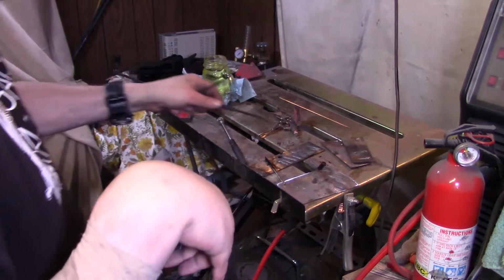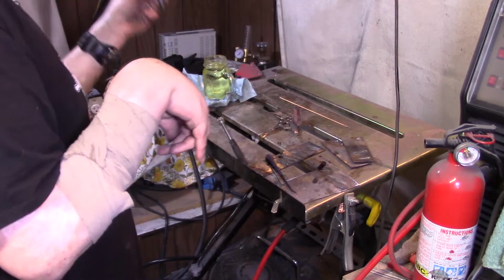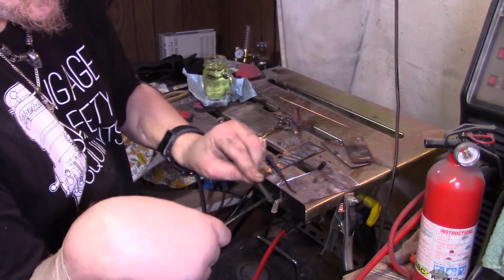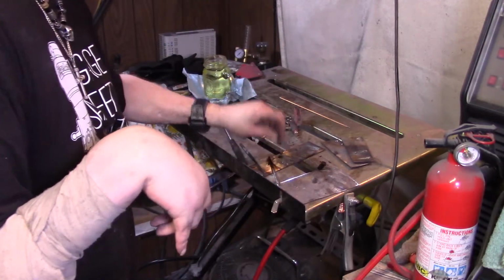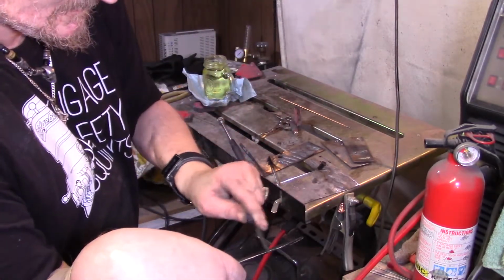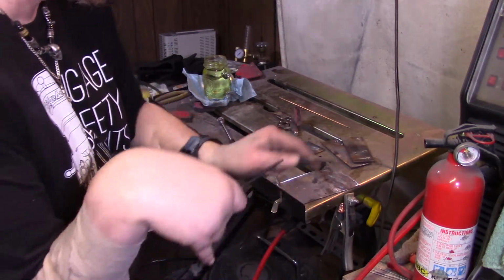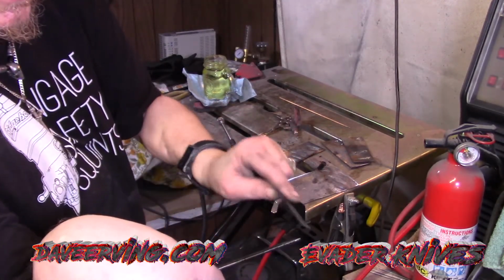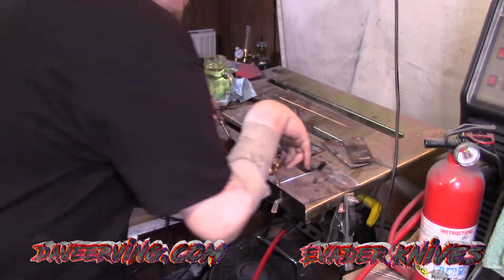All right, just for a little curiosity, here's 65. It skates a little bit, but bites a little bit too. So it's not quite 65. 60 skates. So like I was saying, it's probably like a 62. Actually, I got it all the way up to here. It's like a 62, so we're pretty good.